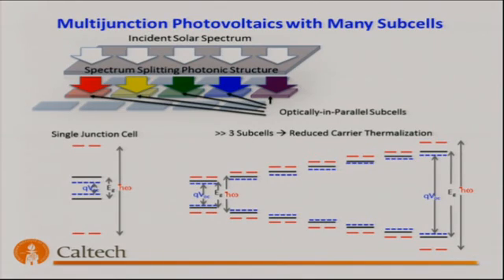And so just before quitting, I should mention that the biggest bar on the chart is the carrier thermalization loss. And to attack that, we think that the most interesting thing to do is to reduce this defect between the photon energy and the band gap energy by making not a triple junction solar cell, but something like an 8 to 10 junction solar cell. And we think that will be the future. We think it should be relatively straightforward, provided we can build a structure that efficiently splits the solar spectrum. Each of these acts essentially as an array of single junction solar cells on a circuit board.